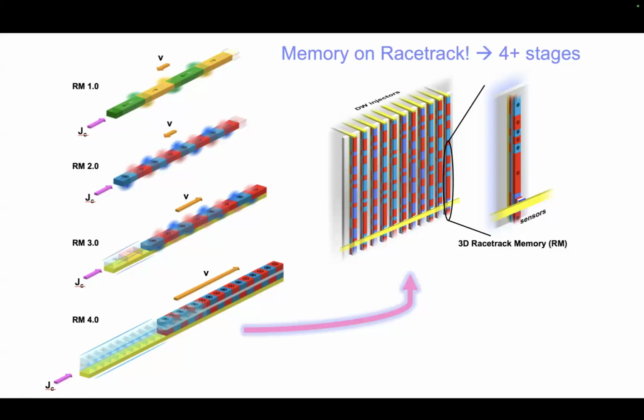And then finally, the most important development is this thing, version 4.0. And this is a synthetic anti-ferromagnetic racetrack. And the reason for this is that the domains and the domain walls, as I mentioned earlier, create stray fields. And this means the strong interaction between the domain walls or domains in one racetrack and the neighboring racetracks, or even in the same racetrack. And on the nanoscale, these stray fields increase inversely with the size of these devices, reaching hundreds of Oersteds. And this means that it's impossible to build a racetrack without eliminating the stray fields.